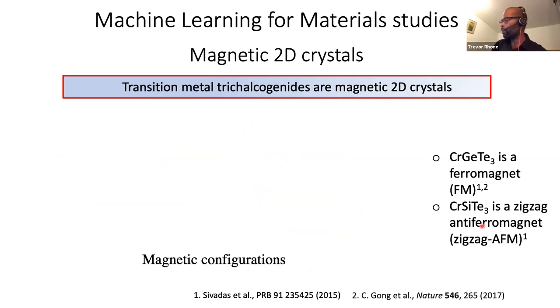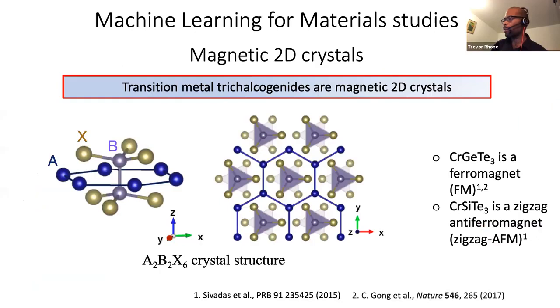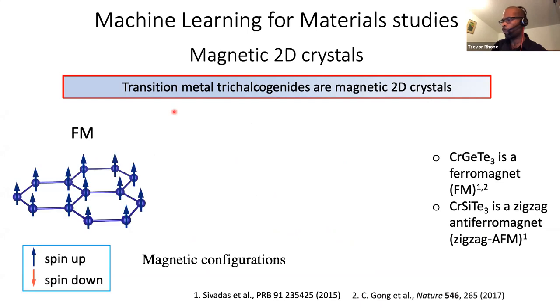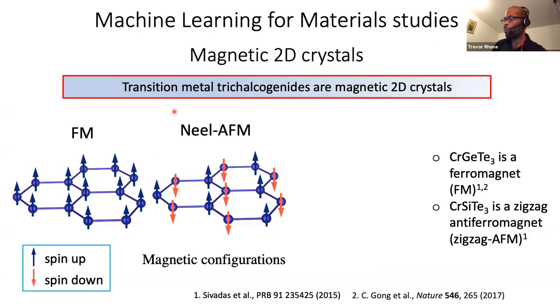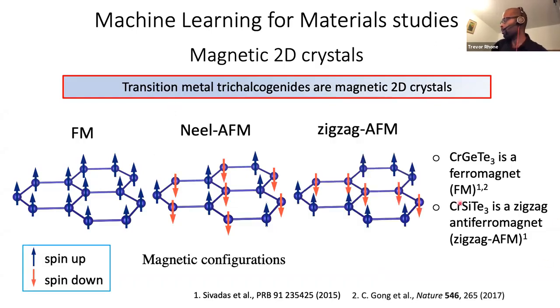And that's what I did. I would decorate these A, B, and X sites in different ways and look at their magnetic properties. I would focus on the ferromagnetic order and also the Néel antiferromagnetic order. It turns out that chromium silicon telluride actually has a zigzag antiferromagnetic order, where along the zigzag edge, the spins are pointing in one direction, and along the other edge, they're reversed. And in the Néel-type AFM configuration, every other spin is reversed. So for the sake of computational expense, I focused on these two magnetic configurations.